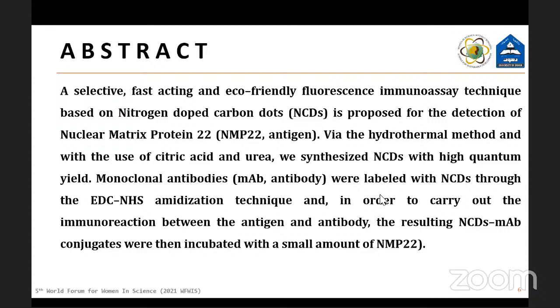According to the abstract, I just mentioned that a selective, fast-acting, and eco-friendly fluorescence immunoassay technique based on nitrogen-doped carbon dots is proposed, and the nitrogen-doped carbon dot is synthesized from citric acid and urea by using the hydrothermal method, and the carbon dot is conjugated with an antibody which is specific for recognizing NMP22. This antibody is a monoclonal antibody.